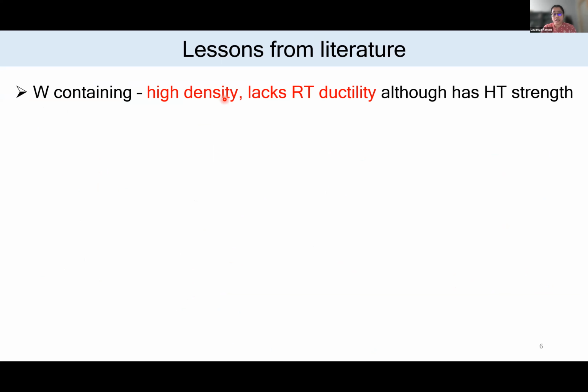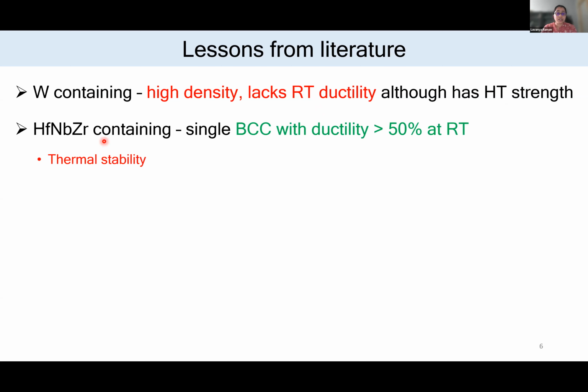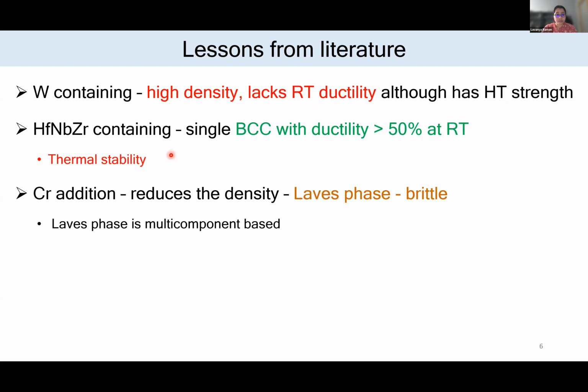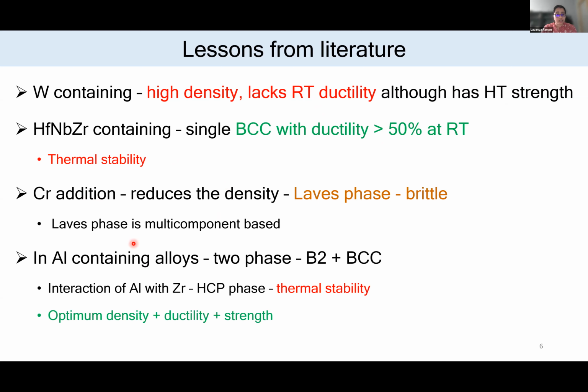Now I have summarized what lessons we can learn from this HEA field. Tungsten containing alloys are highly dense and lack room temperature ductility, but the good point is they have high temperature strength retention. The second class of alloys have adequate room temperature ductility, but the major drawback is thermal stability. They tend to form precipitates or some intermetallic phase upon long heat treatments. And when we added chromium or vanadium, they reduced the density, but the formation of Laves phase made the alloy very brittle. In case of aluminum containing alloys, we have a good combination of density, ductility, and strength, but the major drawback is thermal stability.